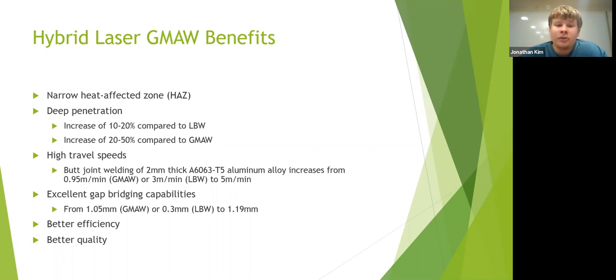The laser beam welding also helps contribute to a lot higher of a speed for the overall hybrid process. An example of this is that there was a 2 millimeter thick aluminum alloy that was tested, and for the gas metal arc welding, it took 0.95 meters per minute. For the laser beam welding, it was 3 meters per minute, and it was able to increase all the way up to 5 meters per minute for the hybrid laser gas metal arc welding process.